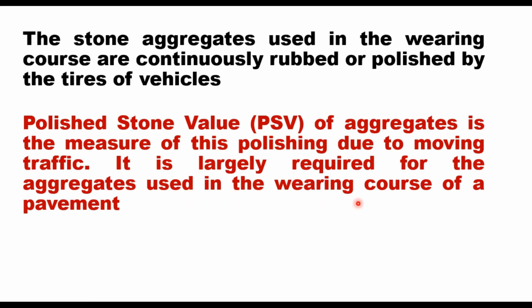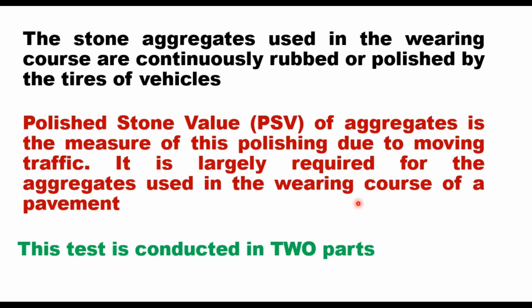Now, this test is conducted in two parts. In the first part, the aggregates are subjected to an accelerated polishing action in a special machine. And then in the second part, the friction value of these polished aggregates is measured using a friction tester, and this value is expressed as polished stone value or simply PSV.